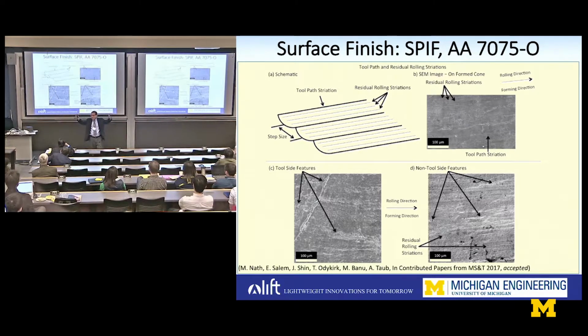Instead of having a stamping die or a deep drawing where the die is basically pulling the material, we're basically doing a wear test. I'm taking a pin on disc and spiraling it through the material. So lots of tribological features on the tool side. And we have a concern of what that means for fatigue. The project we're doing is with Boeing and Lockheed Martin, who are worried about that. But then more importantly, looking at the other side, we're actually seeing some surface cracks.